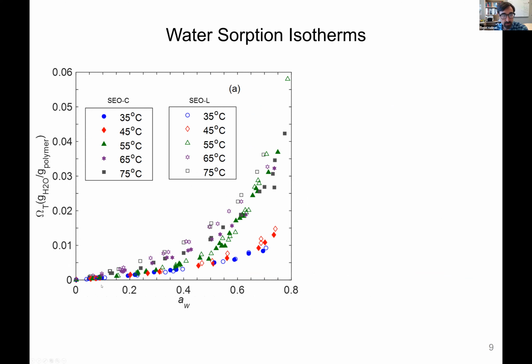You can see here two different classes of water absorption isotherms without actually a big effect of humidity. At low temperature, the crystallinity allows less water to be taken up because the water can only go into the amorphous regions of PEO. When we're above the melting temperature, the purple and grays have a higher uptake of water.